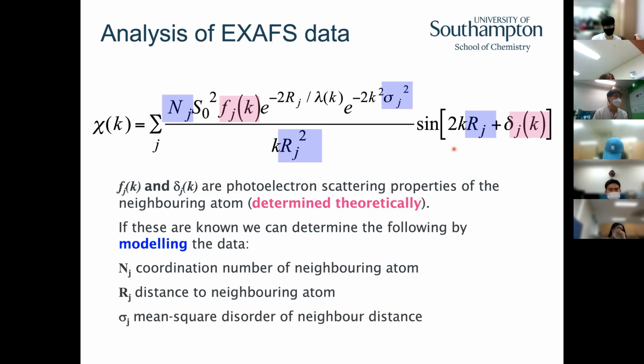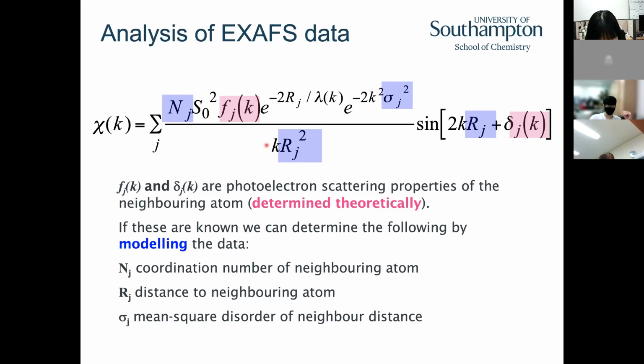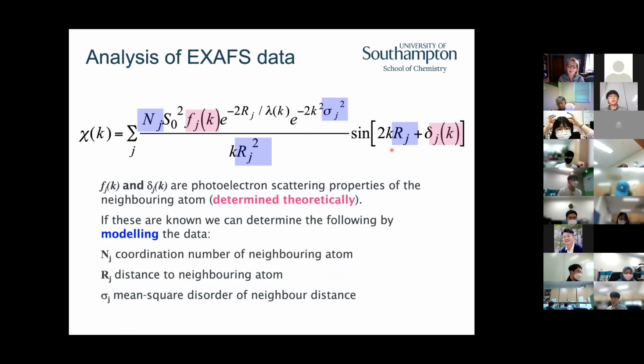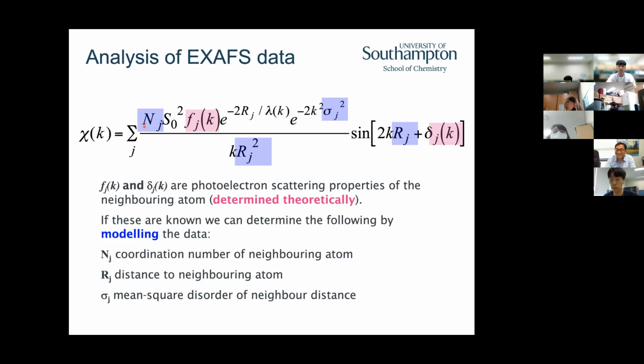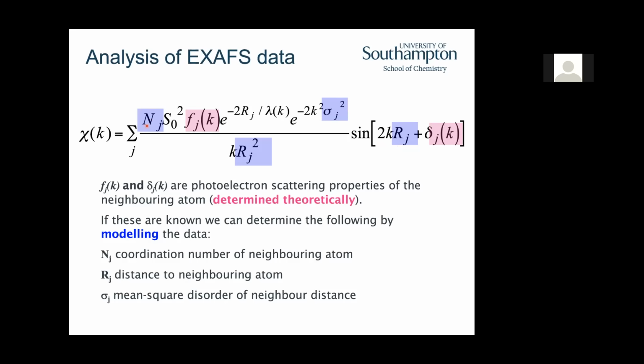And what's really nice is that the distances are in the frequency part of the data, whilst all the other parameters are in the amplitude. So when you're looking at X-ray absorption spectroscopy and people have fit the data, they normally report the distances fairly precisely. But the coordination numbers always have a reasonably large error bar, and that's because they're coupled. These terms are coupled to one another and cannot be separated unless we can collect the data at a large number of temperatures and then fit it.